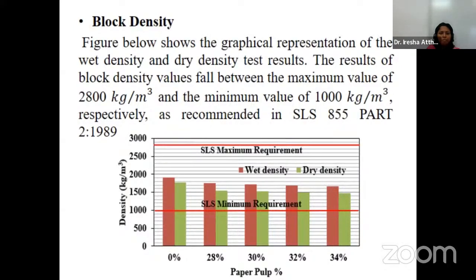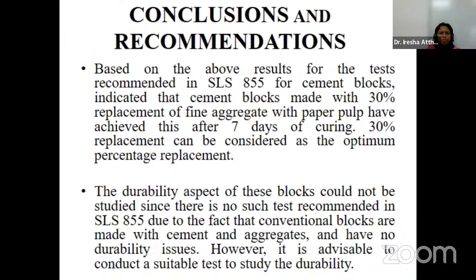At last, this presentation is concluded with the conclusion and recommendation. The primary aim of this research was to produce a lightweight cement block satisfying all the requirements specified in SLS 855/1989, applicable to cement blocks, partially replacing fine aggregate utilizing paper pulp obtained from waste paper. Results of the compressive strength, moisture content, water absorption and block density tests recommended in SLS 855 indicated that cement blocks made with 30% replacement of fine aggregate with paper pulp have achieved this after 7 days of curing. 30% replacement can be considered as the optimum percentage replacement since any further increase in the amount of paper pulp fails to achieve the required compressive strength of 1.2 Newton per millimeter square that is recommended for non-load bearing walls.